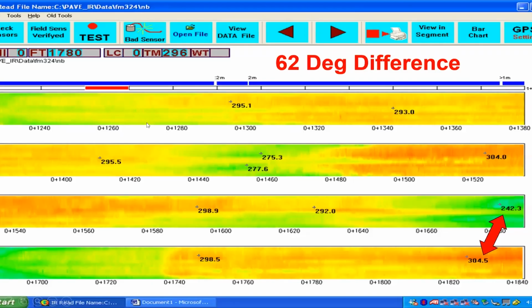And this is why. So if you look at this, this is a kind of a graphic showing thermal segregation, what we run into. A hot load, hot part of the load, cold part of the load. And you can see this by looking at this is as the paver's going down the road. So this would be the right after, and this is at the end of the load. Same thing here, beginning of the load, new load or end of the old load, and then a new load again. Same thing here. So the difference in new load versus the end of the old load or the cold part of the load can be as much as 62 degrees.